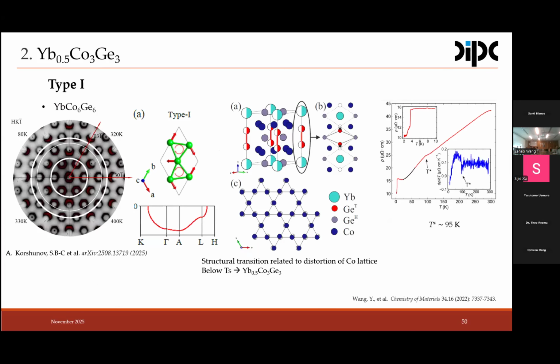It is this one, ytterbium 1/2 cobalt 3 germanium 3, where we again see this hexagonal shape of the diffuse signal. But in this case, you can see how the diffuse scattering is again anisotropic. Here it is isotropic, but if you move out in momentum, the hexagon doesn't close. This compound is the same as 166. It is written 1/233 because there is some twisting and disorder there. Ytterbium occupies some of these germanium pairs.